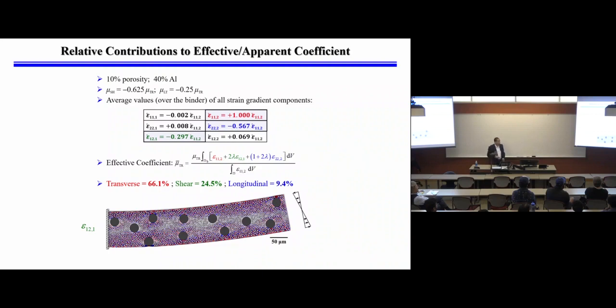And so here is the outcome, right? That's what the overall microstructure will give you in terms of the output. It turns out that if we use the base transverse strain, the horizontal strain gradient in the vertical direction, as the baseline, for the microstructure case it's only 66%, about two-thirds. You actually can enhance it from the shear, which didn't exist if you didn't have the microstructure, or the longitudinal in the vertical direction, the other strain gradient component can give you another 9% to 10%. So that's how you get the enhancement.